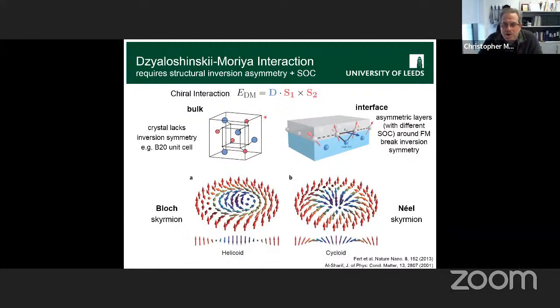Or in the kind of materials we're going to be looking at now, we look at interfaces. So again, we have an inversion asymmetry because there's a different material above you and below you if you're positioned at the interface. And this in fact gives rise to this interaction between 2 neighboring magnetic moments that has this cross product form. So it's chiral, it has a handedness, and if this were all you had, these moments would like to lie perpendicular to one another. Usually what happens in practice is they twist away a little bit from a parallel or anti-parallel state. So you have a ferromagnet, you add a bit of DMI and everything twists a bit.